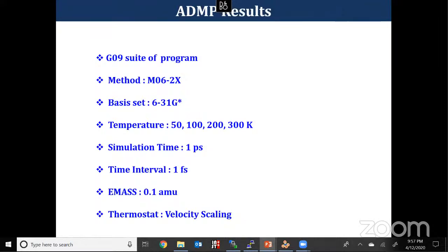After obtaining the desired per hydrogen molecule binding energy as well as gravimetric density, we theoretically wanted to know whether this material will be stable near room temperature or not. In order to do that, I did an ADMP study, that is, the atom-centered density matrix propagation technique available in Gaussian. I chose that method using M06-2X, also a Minnesota functional, produced in the year 2006. I carried out the simulation at 50, 100, 200, and 300 Kelvin with a time frame of 1 picosecond, and a time interval between steps of 1 femtosecond. In order to maintain the temperature, I used a velocity scaling thermostat that helps to keep the temperature at the desired value for the calculation.